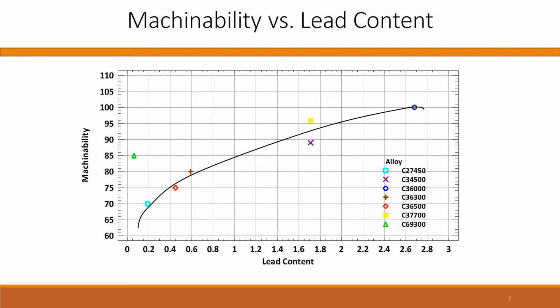But without being able to use so much lead anymore, now there have to be different approaches that are taken to get machinability. And you can see the little green triangle to the left is representative of an alloy called 693, which uses silicon in place of lead to make it more machinable. And there's other options too. You can add bismuth, you can add sulfur, we'll talk about in a bit, or you can add combinations of elements to try to get that machinability high so that the cycle times are short for the machinist, but without having any lead in there.